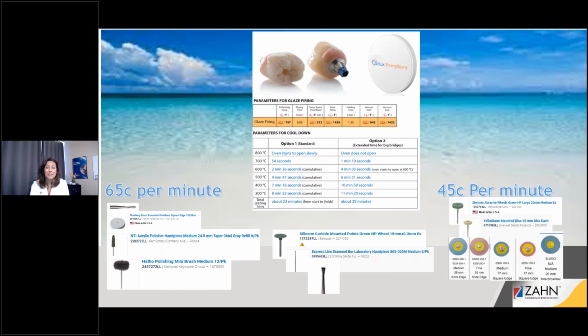That scared me at first. I actually stole that idea from a laboratory I was visiting, and I was frightened when I saw them do it. But as long as you stay away from the margin, it actually leaves a pretty nice finish on the Green State Zirconia. Very smooth. It just really takes it up a notch. So when it comes out of the furnace, there's like no evidence that there was a sprue on there. There's no evidence that you took a rubber wheel to it. It just blends everything very nicely. That's kind of my new second favorite.